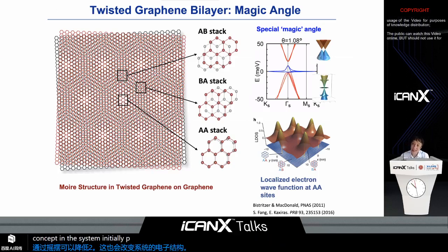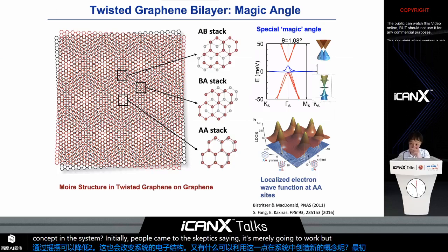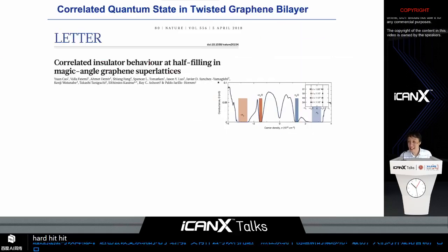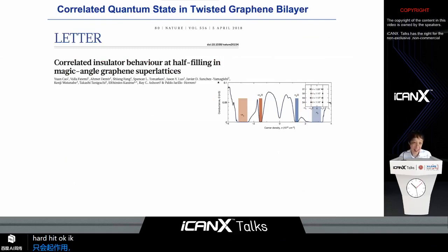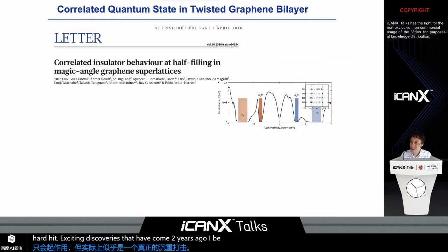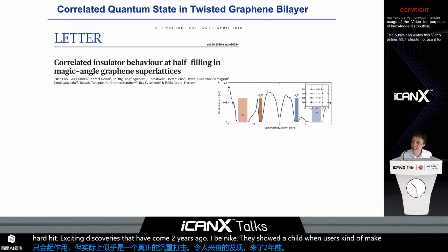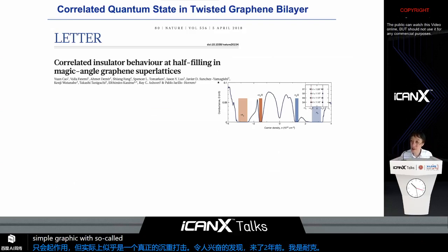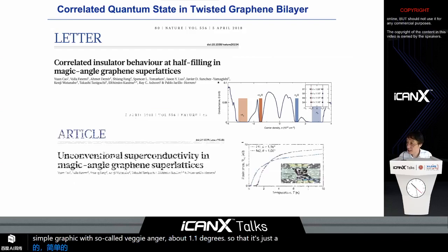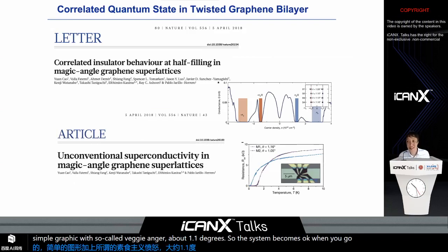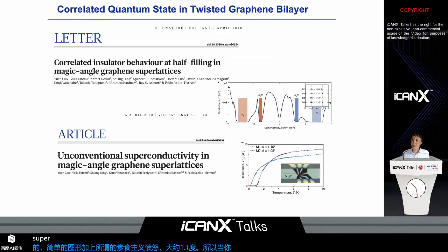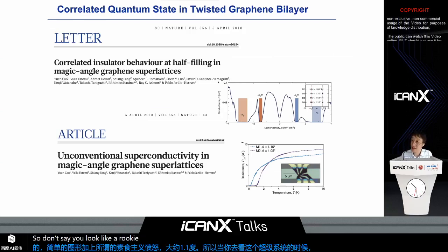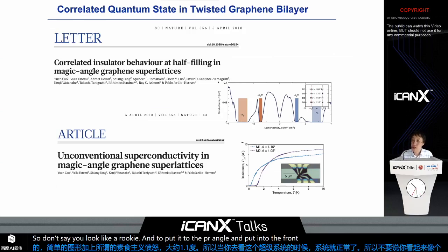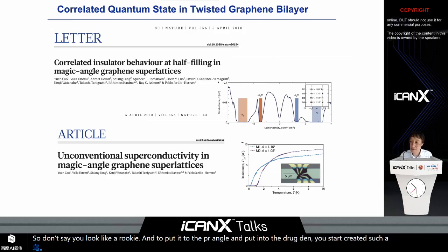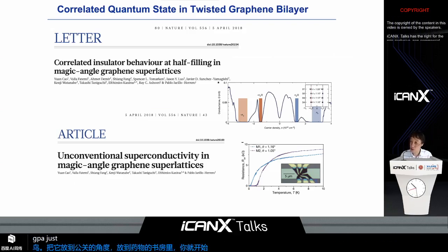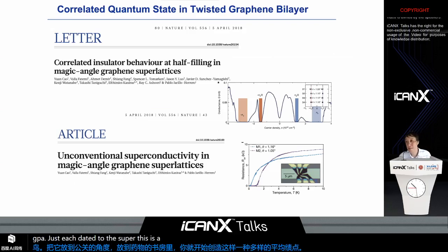Initially, people were already skeptical: is this really going to work? But actually, the field was really hit hard by exciting discoveries that happened 2 years ago by the Pablo Jarillo-Herrero group at MIT. They showed that when you make this twisted bilayer of simple graphene with the so-called magic angle of about 1.1 degrees, suddenly the system becomes insulating. But then when you dope this insulator, suddenly the system becomes superconducting. So it's the same vanilla plain graphene, but simply put into a different angle and a different density, you start creating such diverse behavior, even insulator to superconductor, tunable. This is amazing, the possibility one can provide.